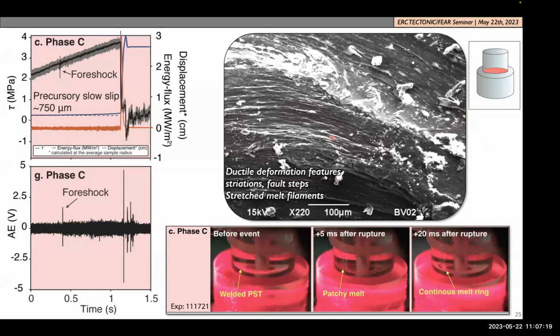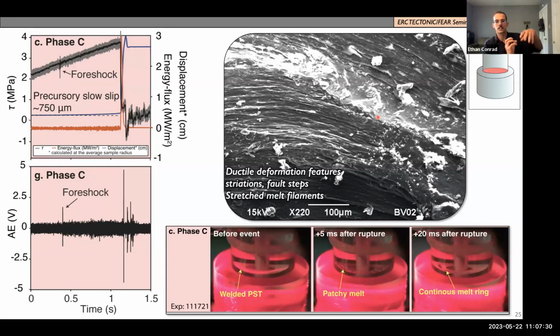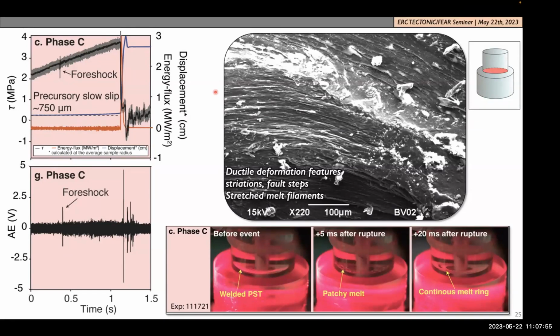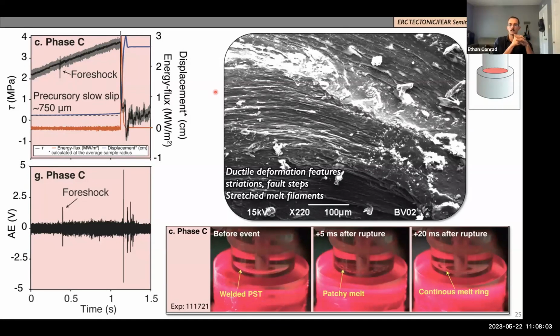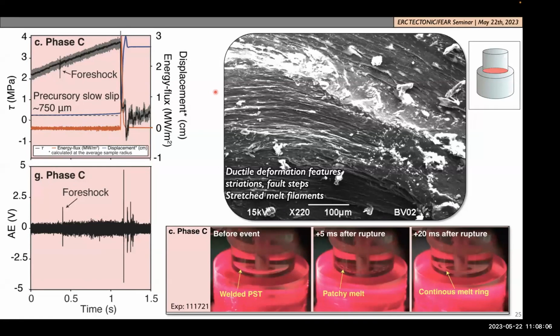So can you tell us what the slip direction is here? It looks like the radius of curvature is changing, so it's not exactly following the striations. So the slip direction, let me just make sure I get this right. I should have put this on here because it's always kind of a brain bender when I start to think about it. So we're loading this way. Okay, so it should be from right to left if I don't have this mixed up. Yes, apologies for not putting that on there. But it looks like the radius of curvature of these striations is not spatially uniform. So they're not all arcs. So some of this, the structure is mostly parallel to the slip direction, but not exactly.